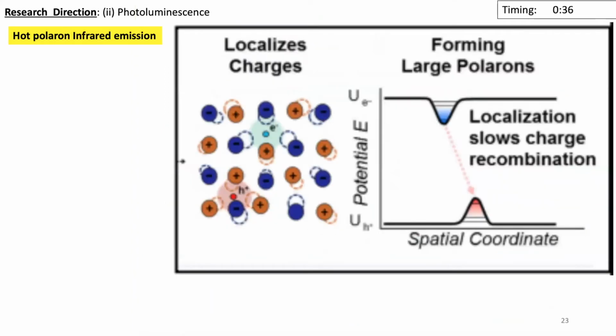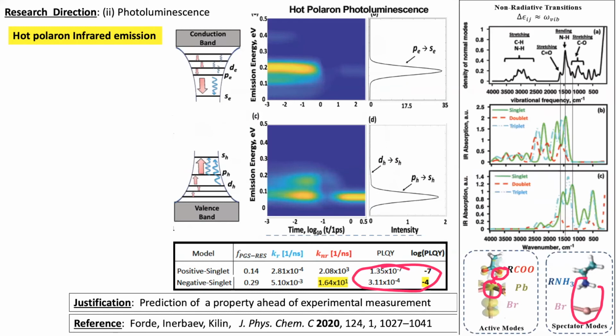So in this situation, if charge is injected in such model, the ions are redistributing. There is some nuclear reorganization, polar information, which changes electronic and optical properties. One can interpret what happens upon injecting charge and re-optimizing nuclear geometry induced by a charge injection as formation of progression of like hydrogen atom-like states.